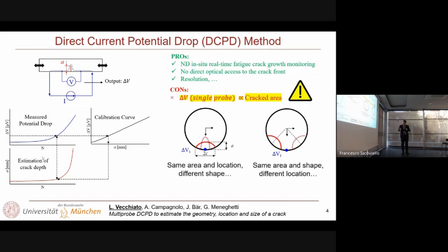But we have the problem that we want to diagnose the size, the shape, and the position of a propagating crack. Let's take for this presentation just a simple example of a semi-elliptical crack propagating on a round specimen. And in this case, with just one single measurement of the potential drop, we can have the same potential drop for cracks having the same location but different shape, or the same shape but different location, or many other combinations of shape, location, and size of this crack.